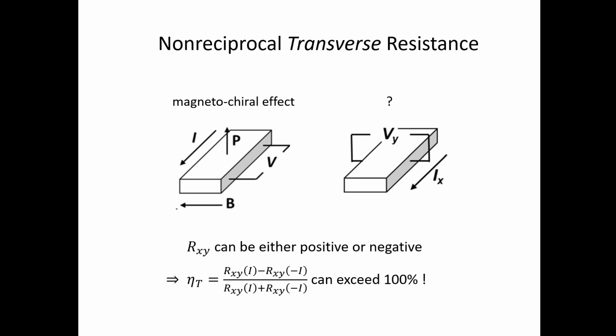So what if we consider transverse resistance? Meaning if we pass current along the x direction, we measure the voltage along the y direction. And the nice thing about the transverse resistance is that it can be zero in the linear regime, or it can be positive or negative. It's not dictated to be positive by the law of thermodynamics, unlike the case of the longitudinal resistance, which has to be positive.